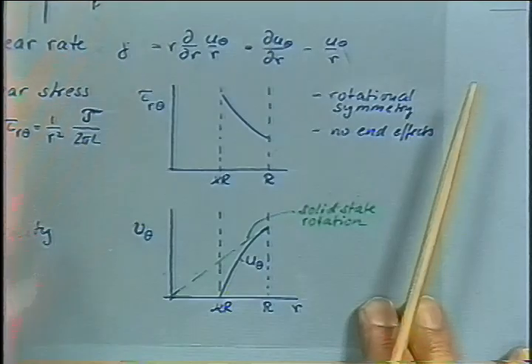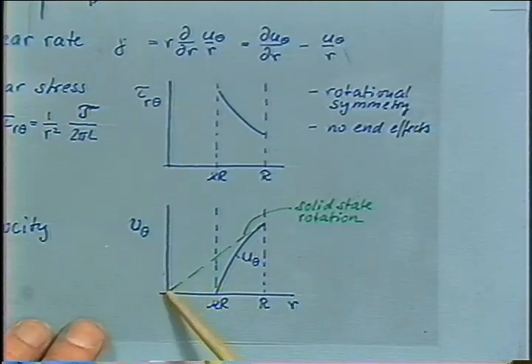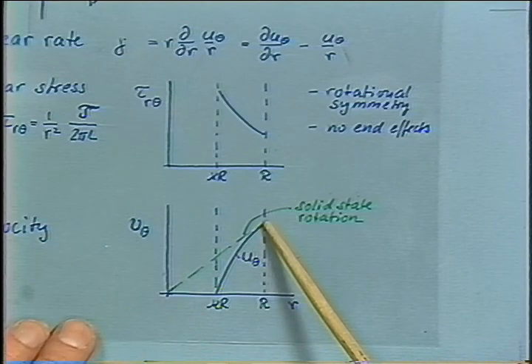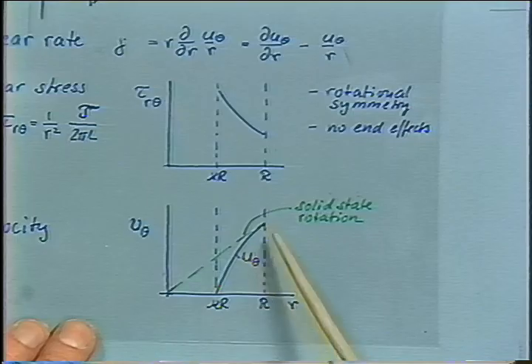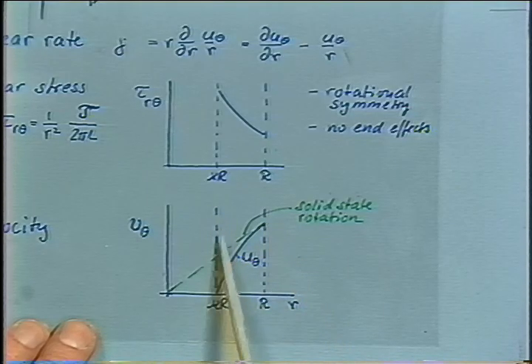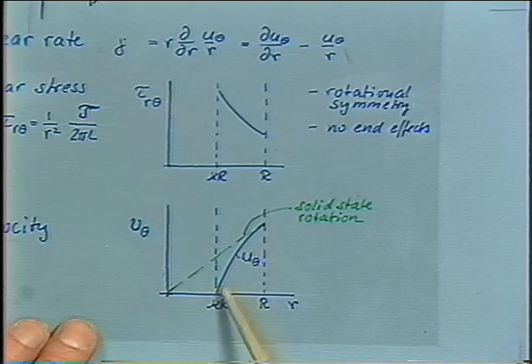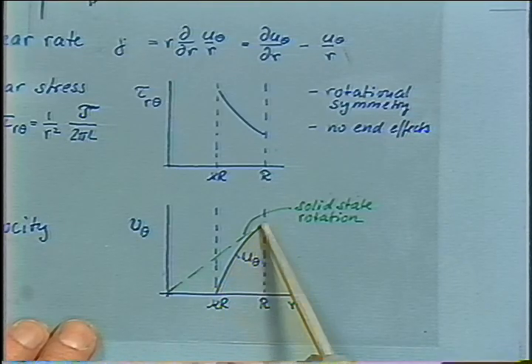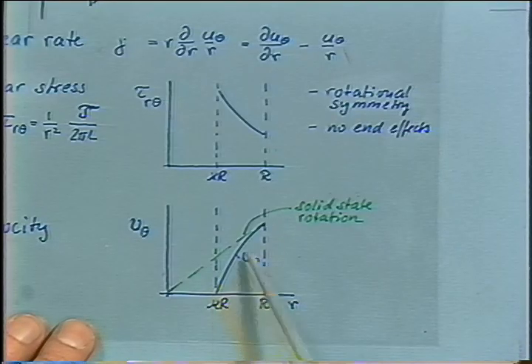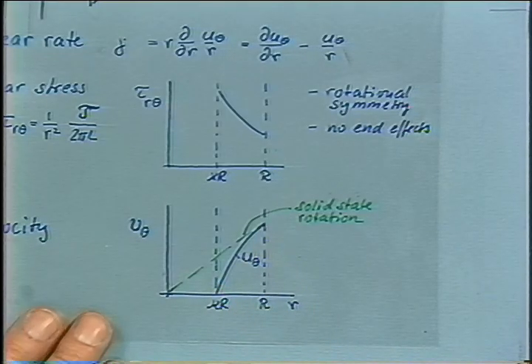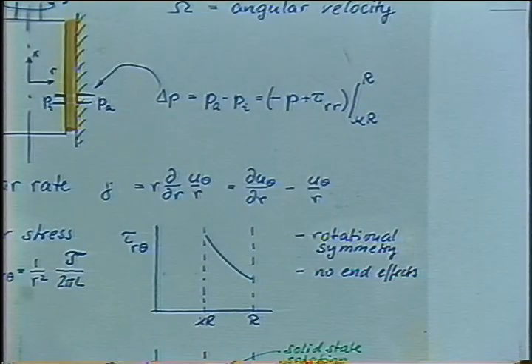I plotted the velocity field down here. The velocity increases linearly from the center to the outside if we have solid state rotation, so if this inner cylinder does not exist and you're just rotating the liquid. But due to the existence of the inner cylinder, which has kappa r as its radius, there is a zero velocity here, and the velocity goes from 0 to its full value. Now, the curvature has to be incorporated into the analysis of the experiment. The shear stress is related to the torque in this fashion. It goes with 1 over r squared. And again, it's not a linear function. The analysis of Couette experiments is somewhat difficult because of that nonlinearity.